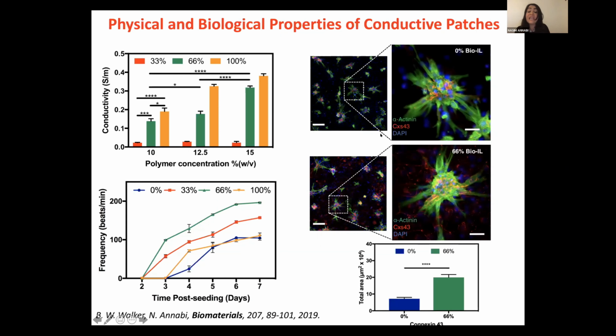So when we wanted to understand better what happened when we have this different beating frequency of the cells, we did immunostaining for different proteins expressed by cardiomyocyte over time. The picture on the top shows a substrate with no electroconductivity. So for this substrate, we did a staining for different markers, such as sarcomeric alpha-actinin, connexin 43 expressed by cardiomyocyte. And we show that as we have no conductivity, the expression of these proteins is lower compared to the formulation that we introduced bioionic liquid, and it has a higher conductivity.